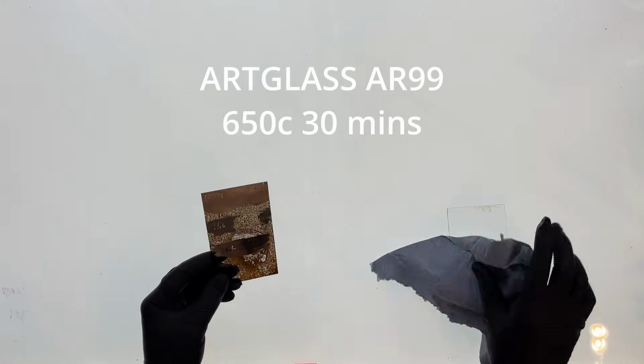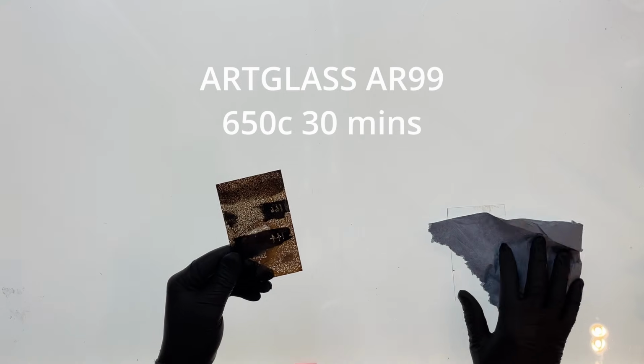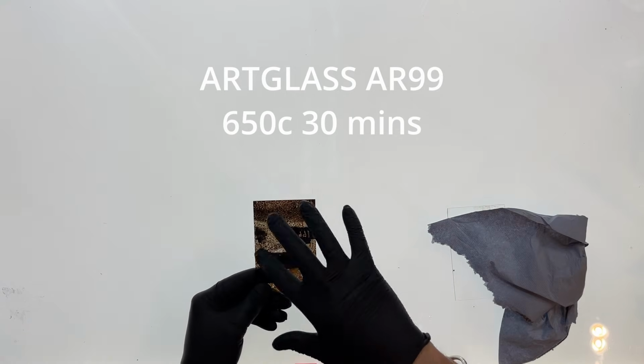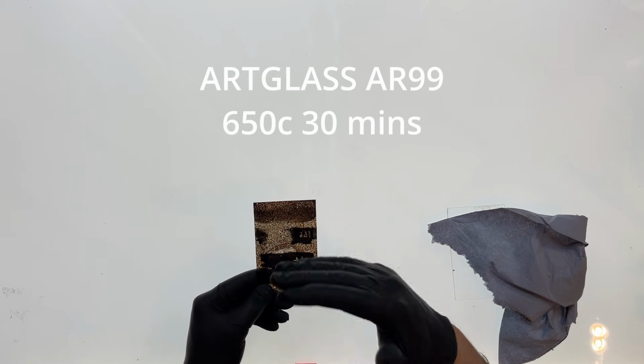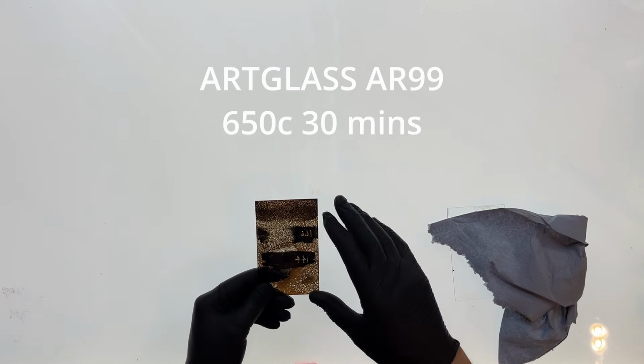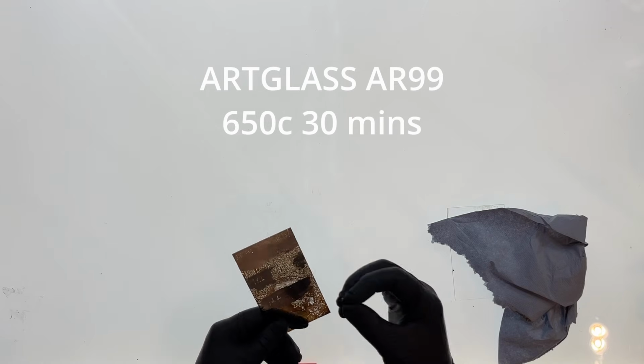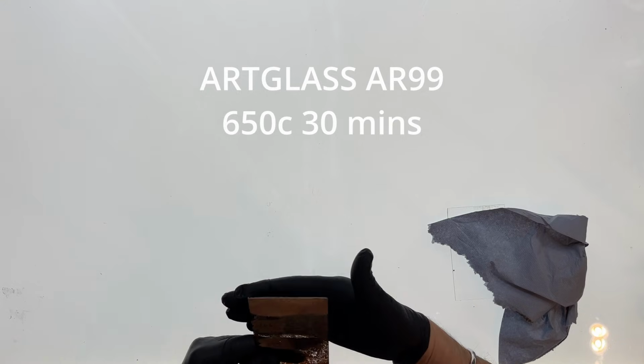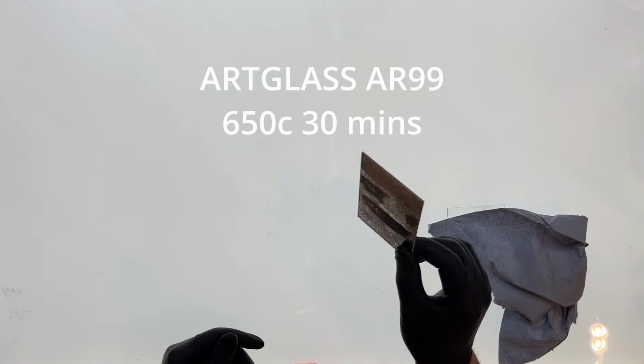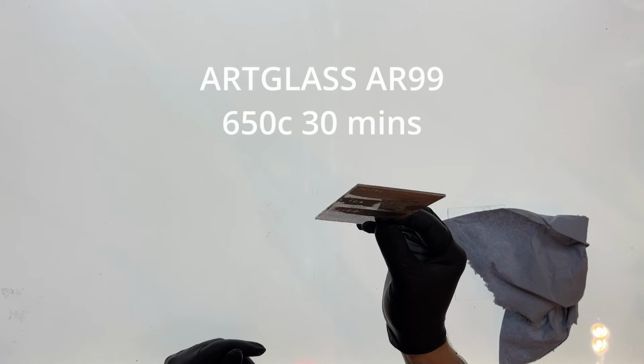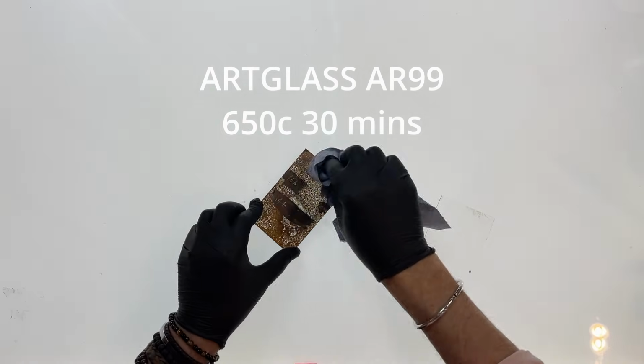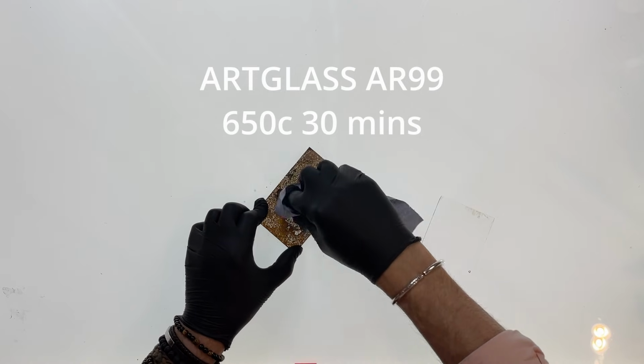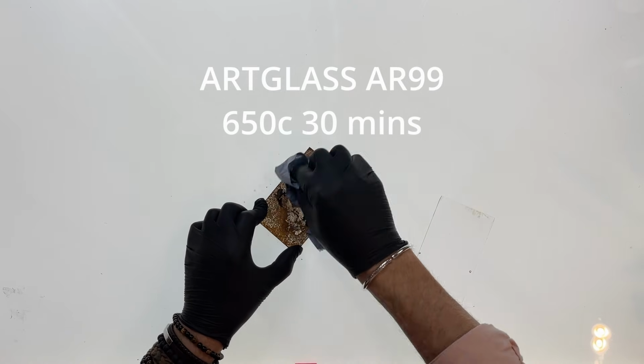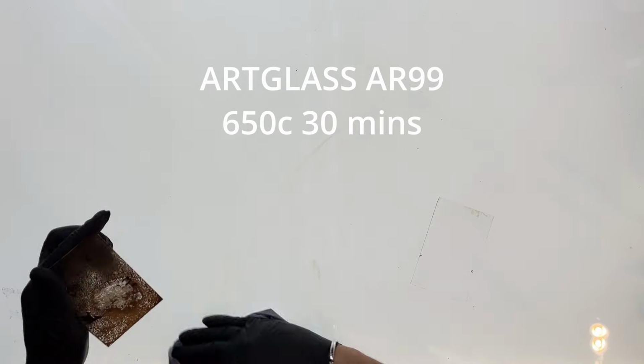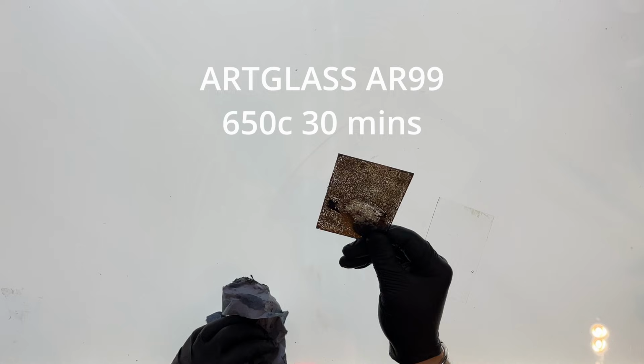Interestingly, this is our AR99, which is our museum quality glass, and as you can see here, it's a complete disaster. It doesn't work at all. There are deposits on the surface of museum glass to reduce the reflective qualities of the glass, and also to inhibit the UV from penetrating through the glass to the artwork underneath. And those chemical additives are having a profound effect when you fire them in the kiln. They've completely burned. This is the ruby red stain here, and as you can see here, again, there is no reaction to this. So I can safely say that the AR99 museum quality glass does not react well to being put into the kiln.